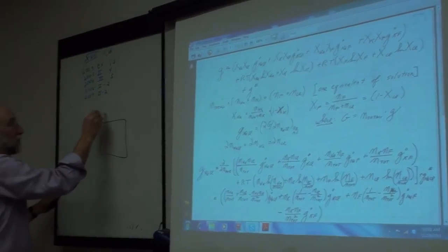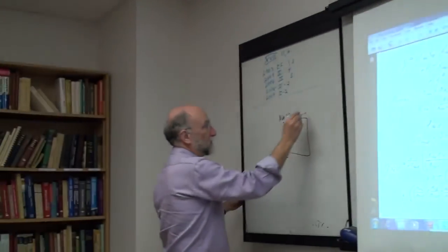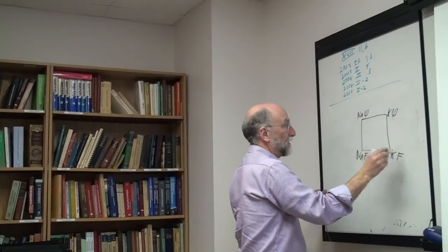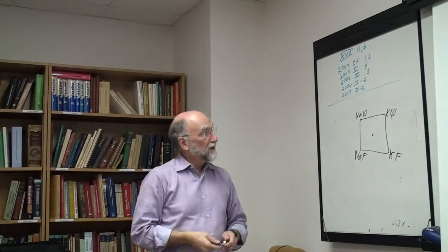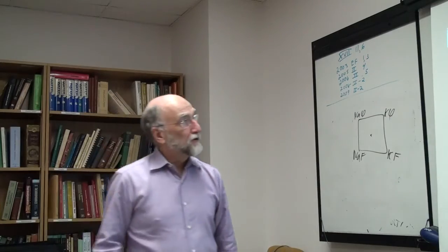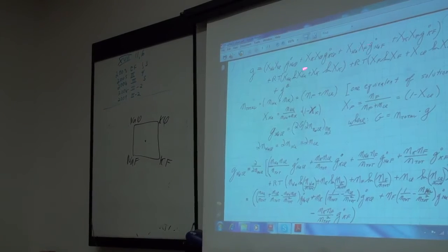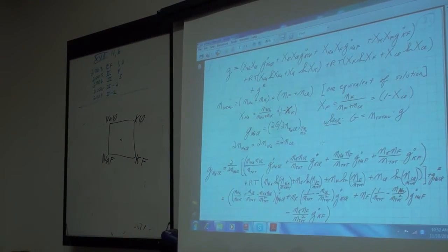So this goes back. So here we have sodium fluoride, potassium fluoride, and I'm trying in that system to get an expression for the activity of sodium chloride. And the main terms are the end member terms, the product of the site fractions times G naught, the four terms, plus the ideal mixing term on each sublattice. GXS terms are your alpha terms, plus your short range order correction, which we'll ignore for the moment because these are the most important terms, especially in dilute solutions.